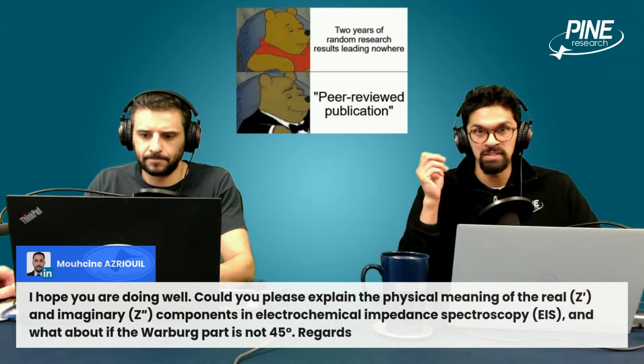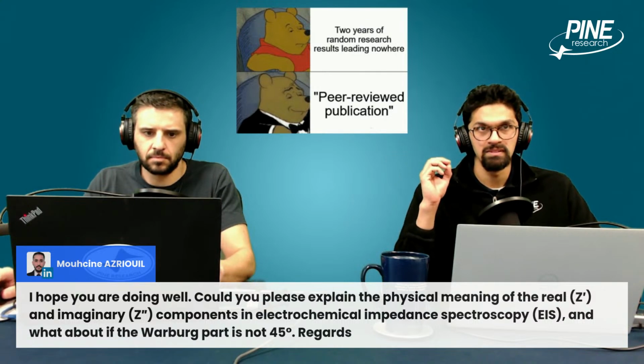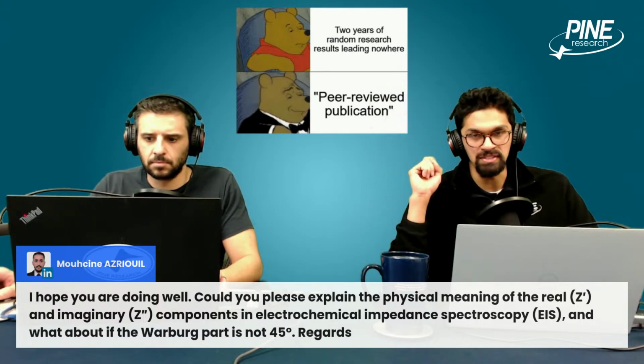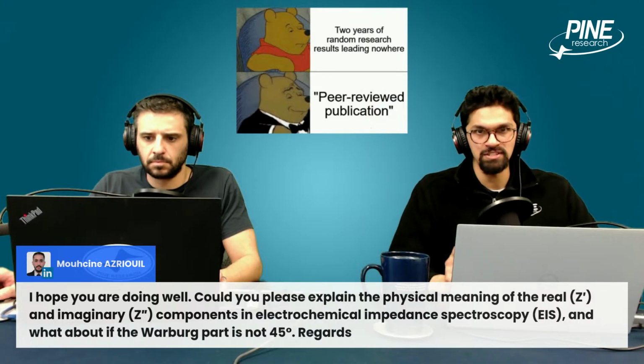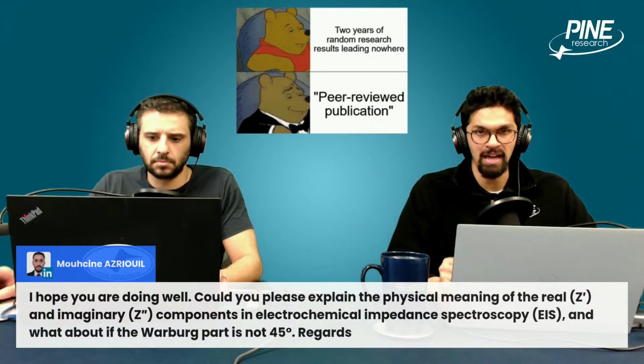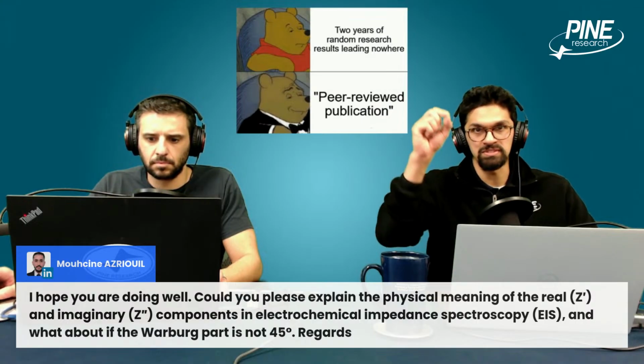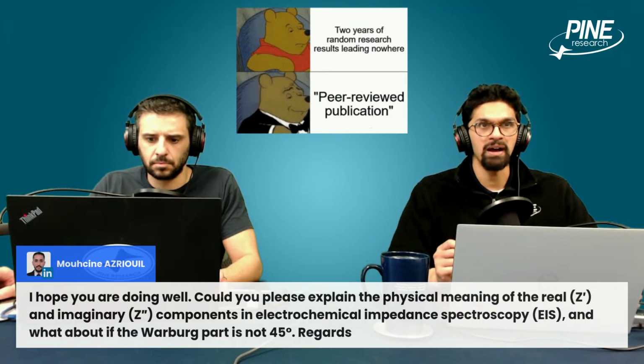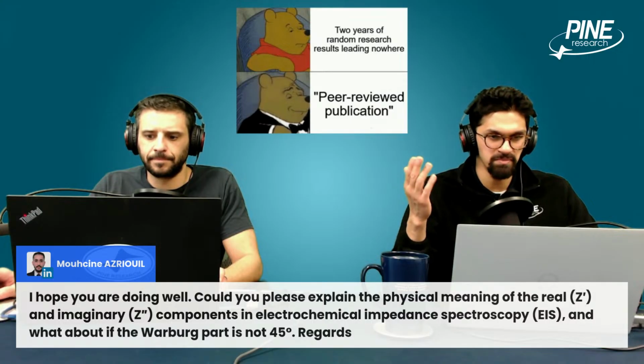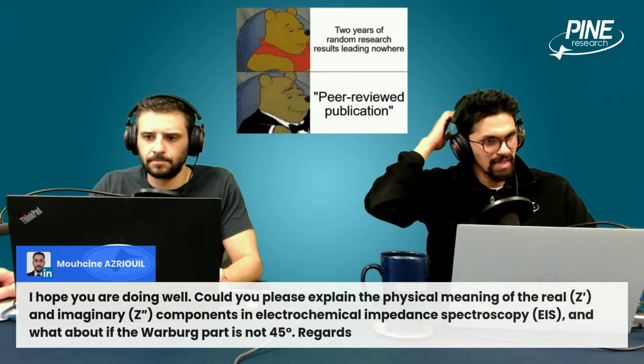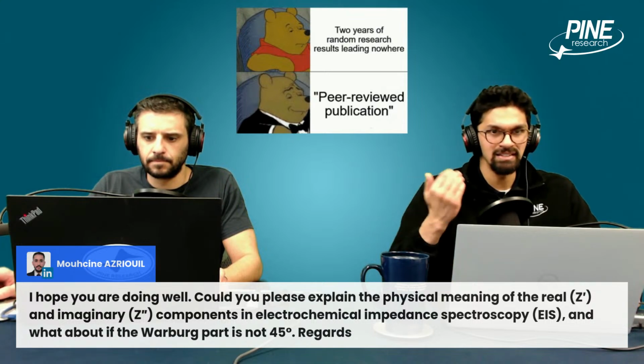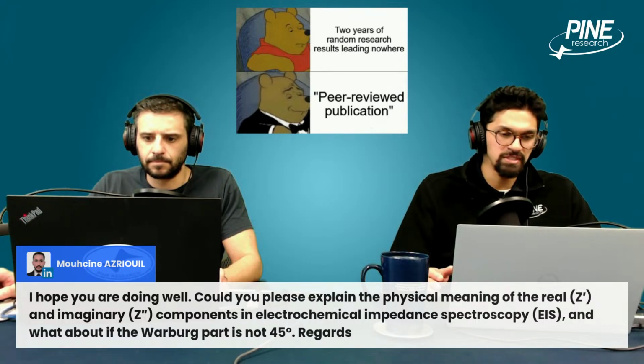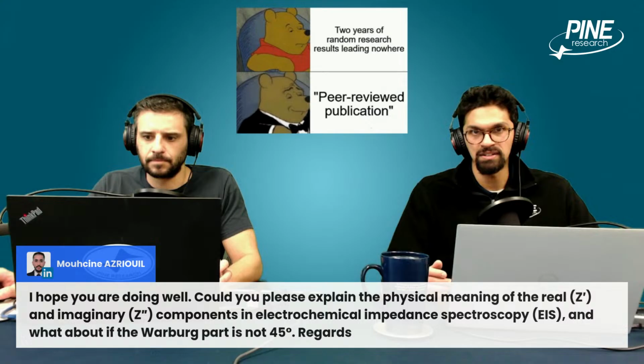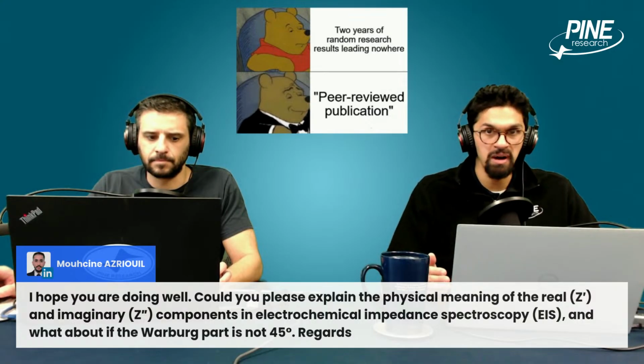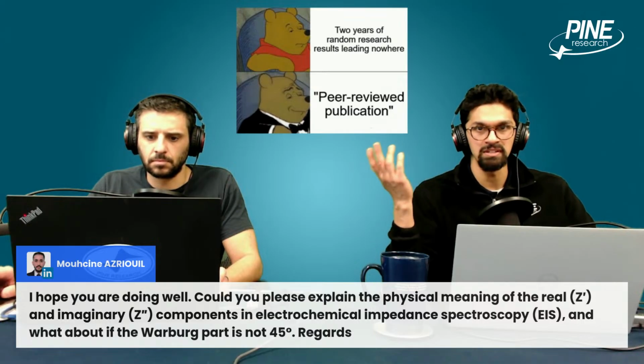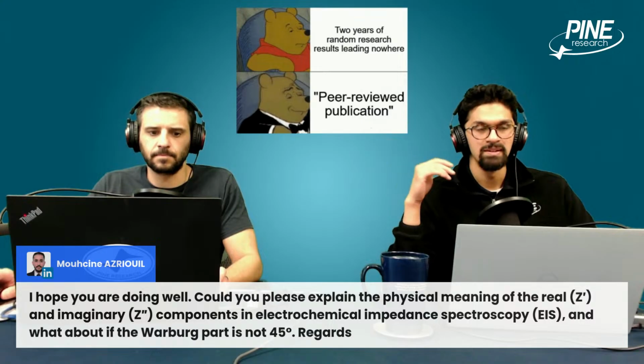The long story short is that 45 degrees about the origin of a Nyquist plot means that the real and the imaginary impedance grow proportionally at the same rate, right? They're both equal to each other. And in the case of Warburg impedance, we're talking about diffusion, molecules moving and how hard it is for the molecule to move, and the lag in the time response. You end up thinking about the Warburg impedance and its 45-degree angle as the speed with which a molecule is moving, whether through a membrane or just in a semi-infinite solution phase. You get this 45-degree angle.